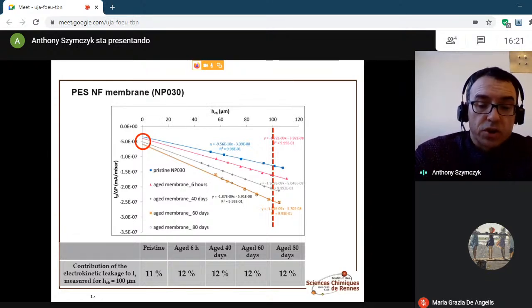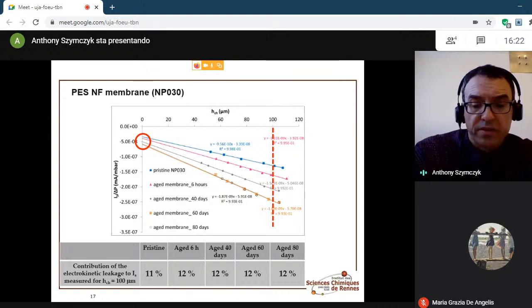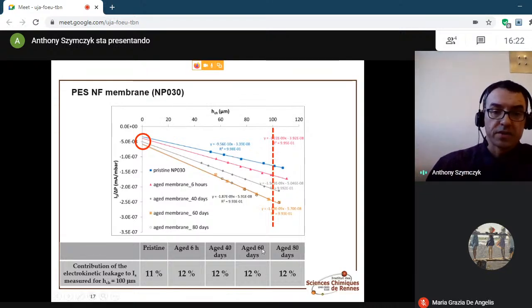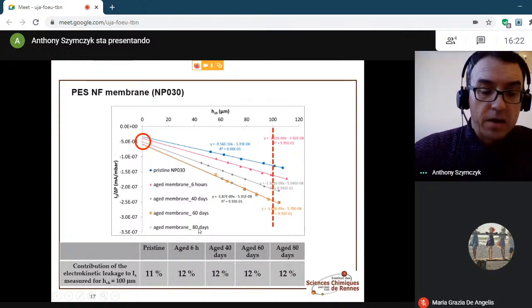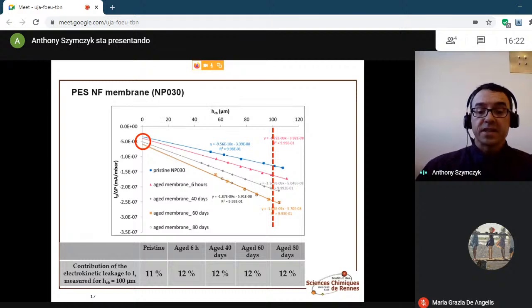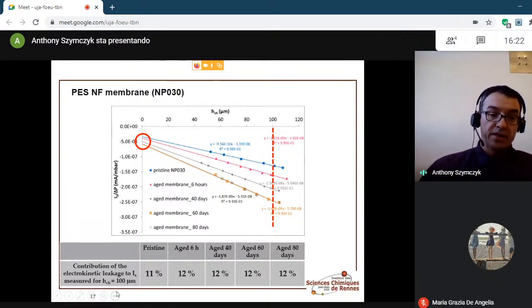For this first example, I've chosen to show you the results of streaming current experiments carried out with a nanofiltration PES membrane, polyether sulfone, that was exposed to sodium hypochlorite solutions for different times, ranging from 6 hours to 80 days. Measurements were taken at different separation distances between the samples in order to determine the intensity of the electrokinetic leakage. The table shows the contribution of the electrokinetic leakage to the experimentally measured signal, considering the signal measured at a distance of 100 micrometers as an arbitrary reference.